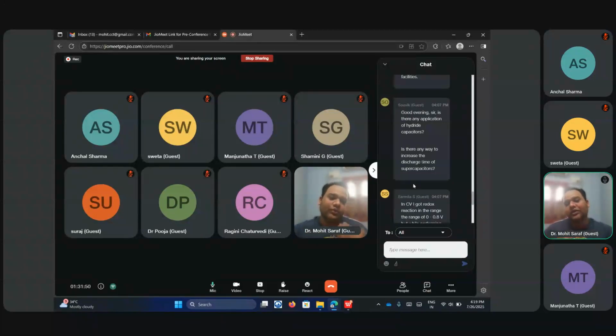I think you want to ask how to increase the capacitance. I have provided enough methods for how you can increase capacitance by tailoring the morphology. You can somehow reduce the path length, access the electrode surface efficiently by creating short diffusion channels, and add some electrically conducting material or additive to your system. Then you can improve your performance, along with having a large surface area of your electrode structure so you can capture more electrolyte ions.